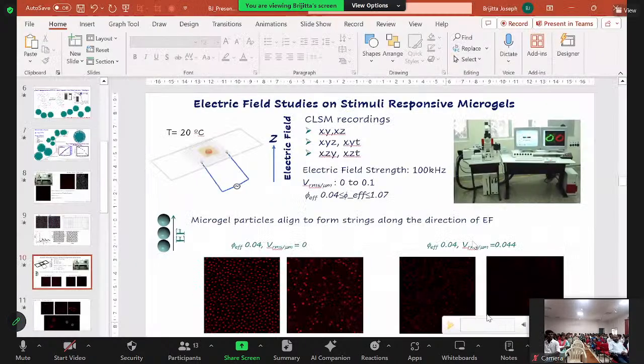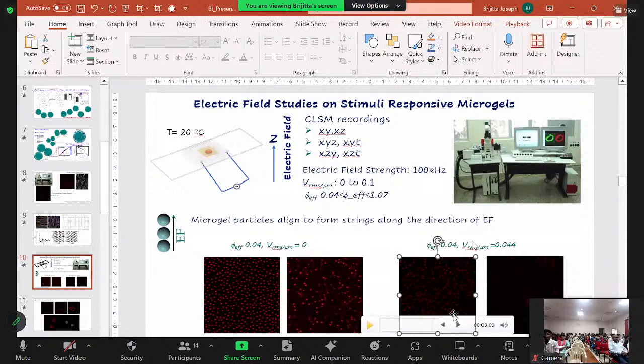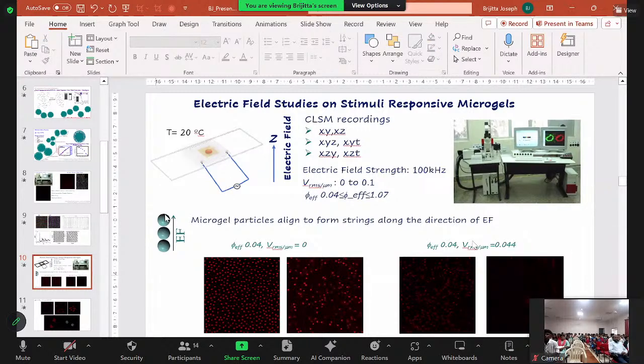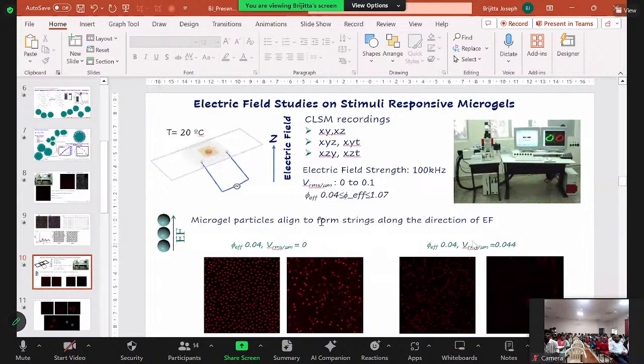So if you see here, the picture is quite different from what you see in the previous image. Here you can see the particles undergoing not Brownian dynamics, but a sort of arrested dynamics. And if you see the XZ plane, the particles are arranged in the form of strings. When you put microgels, or any colloids, in an electric field, they form dipoles, and dipole-dipole interaction leads to the formation of strings in the direction of the electric field.